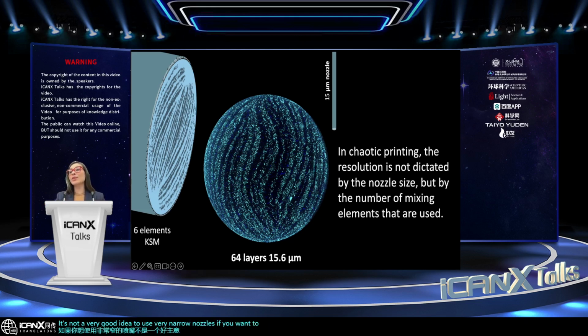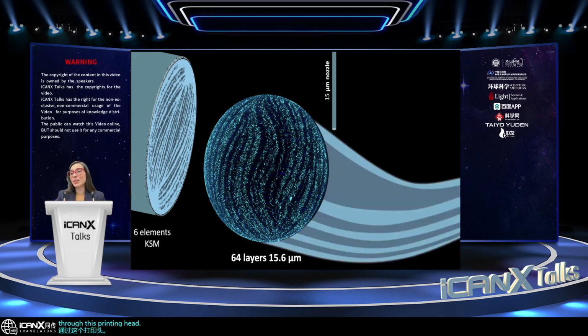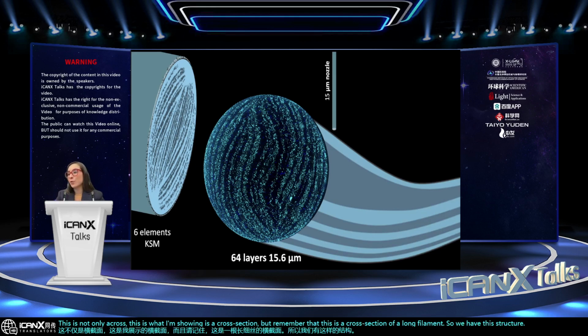In chaotic printing, the resolution is not dictated by the nozzle size, but by the number of mixing elements that you are using. And the outlet can be huge. It's 1 millimeter in diameter, so the cells don't even notice that they are being extruded through this printing head. What I'm showing is a cross-section, but remember that this is a cross-section of a long filament. So we have this structure within the whole construct, which is also something that we find very useful for bioprinting.